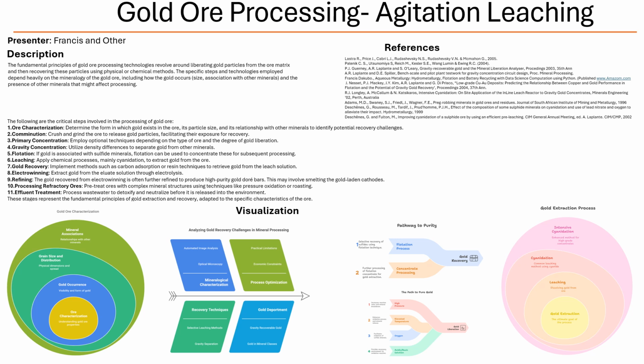Now, what happens to the concentrate after it's been recovered by gravity? I know that traditionally they used a process called tabling to further upgrade it, but the notes suggest that there's a new kid on the block. Yeah, tabling is still used in some cases, but it's definitely becoming less common. The trend now is towards intensive cyanidation of those gravity concentrates. Intensive cyanidation. So that's using cyanide to leach the gold from the concentrate. Exactly. But because the concentrate is already enriched in gold, you can use a much higher concentration of cyanide and often higher temperatures and pressures as well.